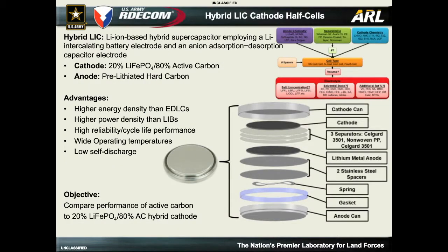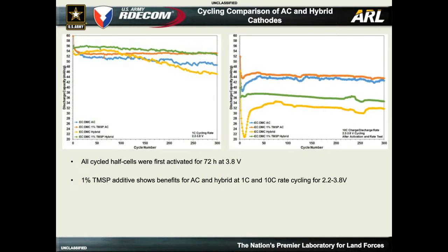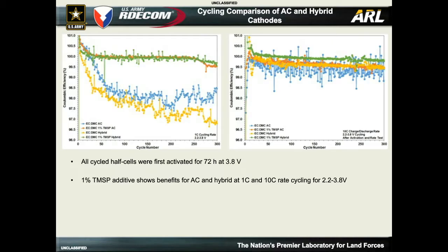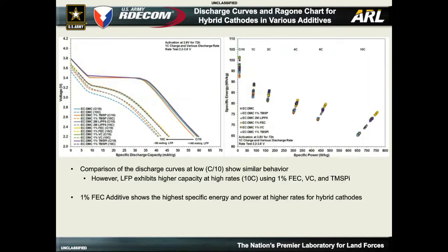Again, I mentioned some of the work that we're doing is looking at hybrid lithium-ion capacitors. So you're adding some lithium-ion battery cathode material in there, trying to get the energy density up and yet retain the fast charge rate. So that work is ongoing. And again, this just shows some cycling data with those hybrid electrodes. And then here, this shows how the additive actually improves the cycling efficiency. If you look at the chart on the left there, the additive has a significant effect on charge-discharge efficiency of these systems. This just shows the actual discharge curves. I'll skip over that.